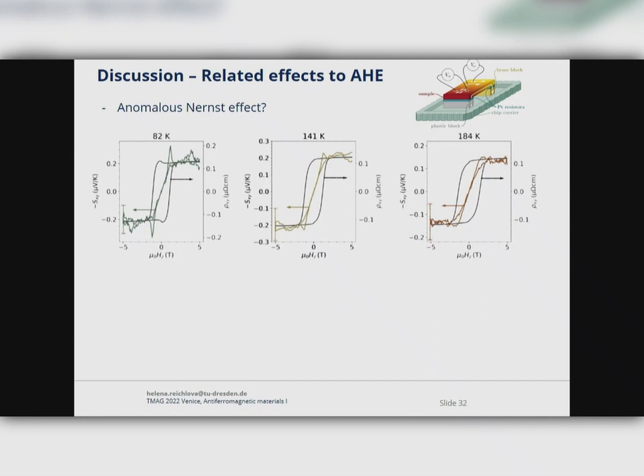We see that the anomalous Nernst data share some common features. They share the same saturation field. They are also more or less constant in the full studied temperature range. However, there is also a striking difference, and this is the absence of the coercive field in all anomalous Nernst data. We already excluded some obvious experimental artifacts, which I don't have time to speak about, but this is definitely a thing which we wonder about right now: why one has the broad coercive field and one does not. Again, a topic for discussion, and I'm happy for any ideas.